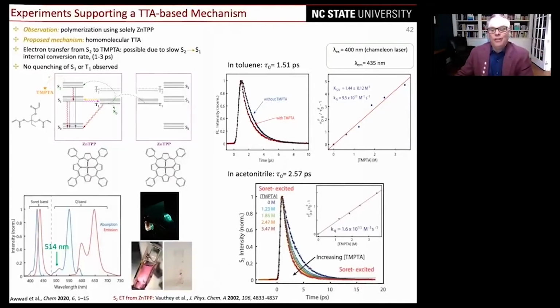And what you then do is in toluene, this is the S2 fluorescence of the porphyrin. And then if we add the TMPTA, which I told you is a dangerous experiment because it polymerizes, you see the lifetime shorten. A better experiment is in acetonitrile where things are more soluble and the lifetime of the porphyrin is a little longer.